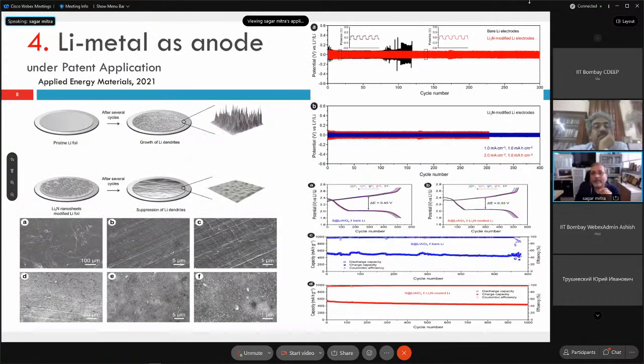Another thing I talked about is lithium metal. So instead of graphite, can I use lithium metal? That's what people are working on right now. But lithium metal has a problem. Once I use lithium metal on the anode side, there is a lot of dendrite formation, because lithium doesn't deposit in a uniform way.